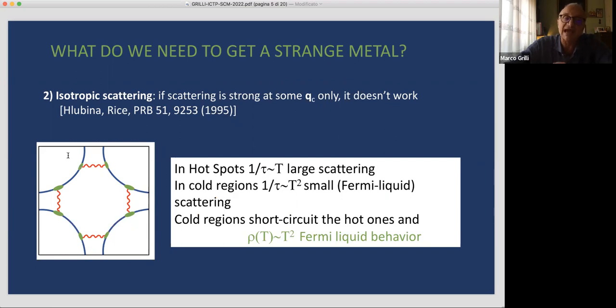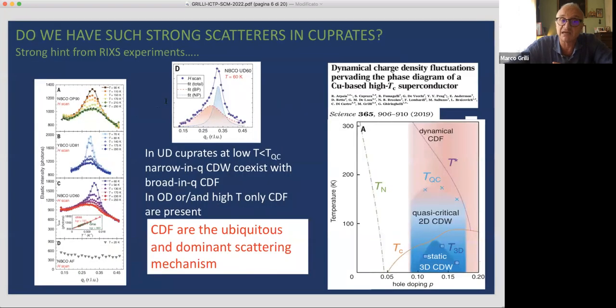So spin and charge density waves in the underdoped region and optimally doped region can cooperate for the pairing, but the charge density waves, the peaked object here. Instead, if you go here in the overdoped region where there are charge density fluctuations only, then they can neither change the Fermi surface shape nor mediate pairing because they are repulsive.